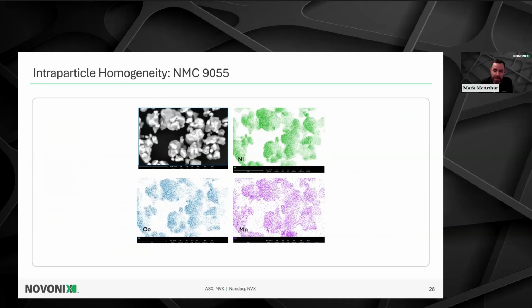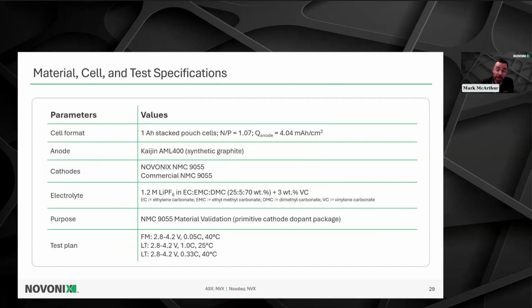Again, the homogeneity of the material, the nickel, the cobalt, the manganese are all very well intimately mixed within the powder. So that is going to lead to decent performance in a battery cell. And we, again, constructed 1 amp hour stacked pouch cells and conducted very similar test protocol to what I showed for the NMC 811 work, either cycling at 25 degrees Celsius or 40 degrees Celsius at 1C or C/3 respectively.